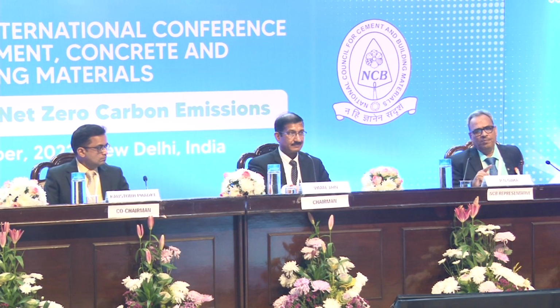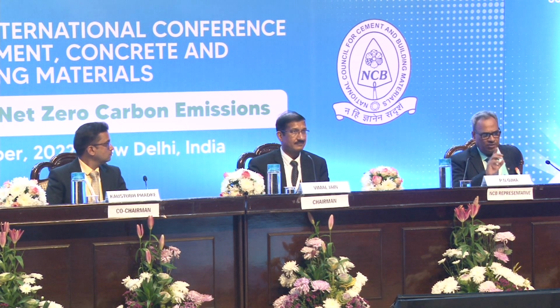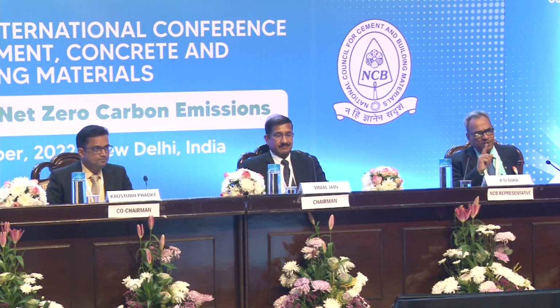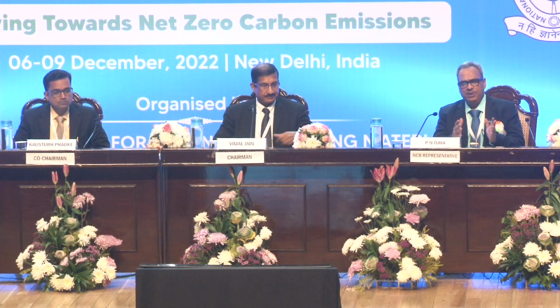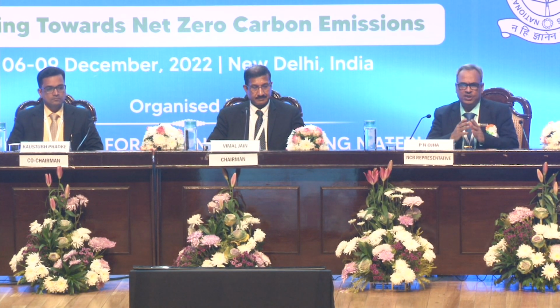The pH of concrete per se is important; the pH of aggregate is not important. So from where are we getting the pH in the concrete system? We are getting it from the cement: first the dissolution of alkalis, and then after reactions, the reserve alkalinity is calcium hydroxide. So we are not getting pH from the aggregate. So if you are producing aggregate and it has a lower pH, that will not affect the durability of concrete per se, with respect to reinforcement corrosion, which is primarily thought of as carbonation-induced corrosion. So manufacturing an aggregate having a lower pH value will not affect the durability of concrete as far as my scientific knowledge is concerned. But that will have to be established in the laboratory when you are producing the aggregate. That was my point.